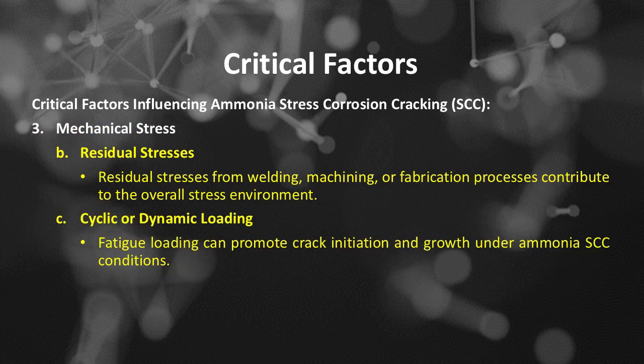Number B, residual stresses. Residual stresses from welding, machining, or fabrication processes contribute to the overall stress environment. Number C, cyclic or dynamic loading. Fatigue loading can promote crack initiation and growth under ammonia SCC conditions.